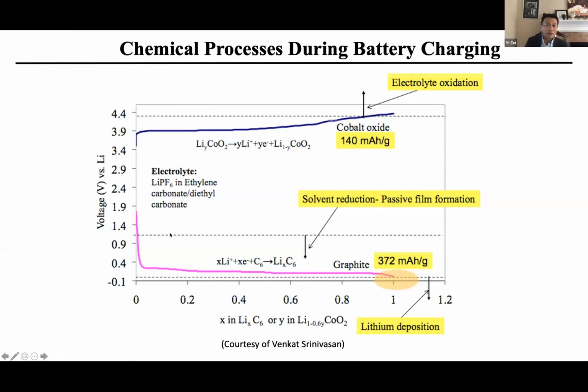And right here, for the SEI formation, below roughly 1 volt, 1.2 volt, you start to decompose the electrolyte, forming this solid electrolyte interface. On the cathode side, as you charge it up, the potential goes up, and you see the plateau. Once it goes over a certain voltage, roughly 4.2, 4.3 volt, you start to worry about electrolyte oxidation. The anode side is the reduction, the cathode side is the oxidation. The temperature will accelerate oxidation on the cathode side. So that's something you need to think about once the thermal issue really comes in.